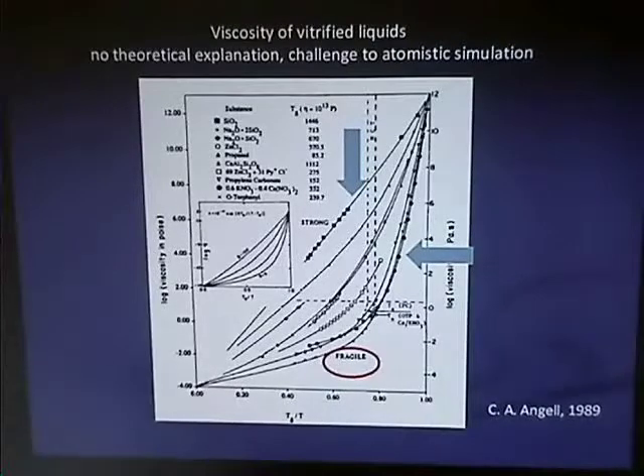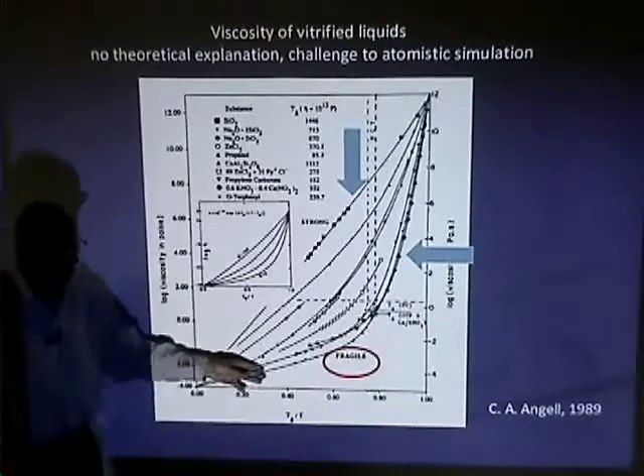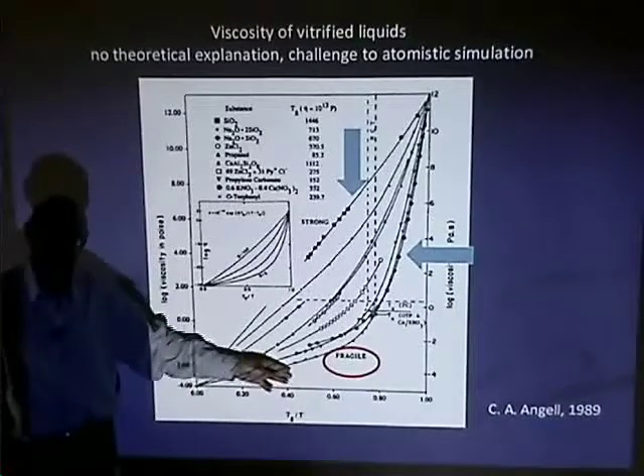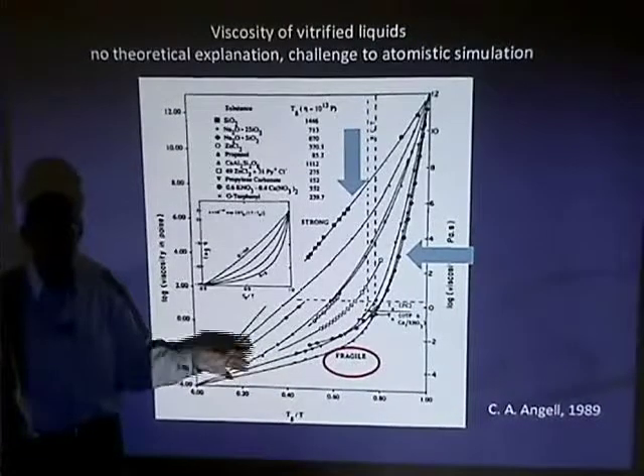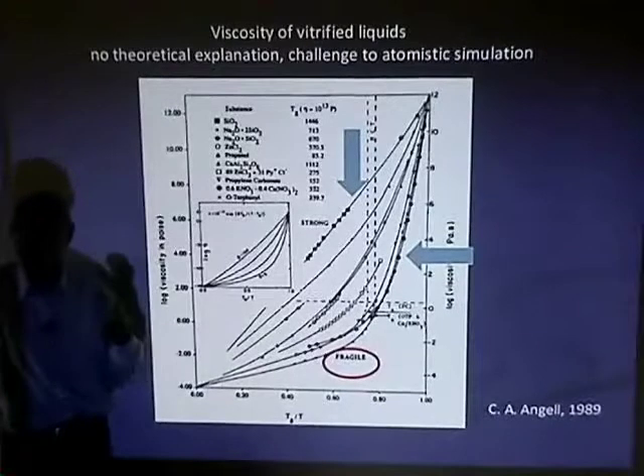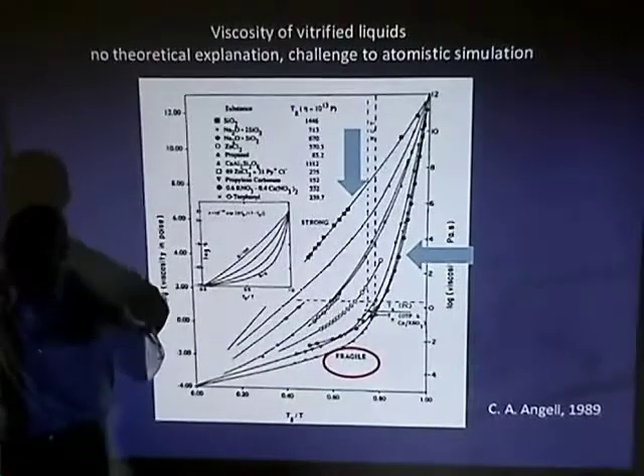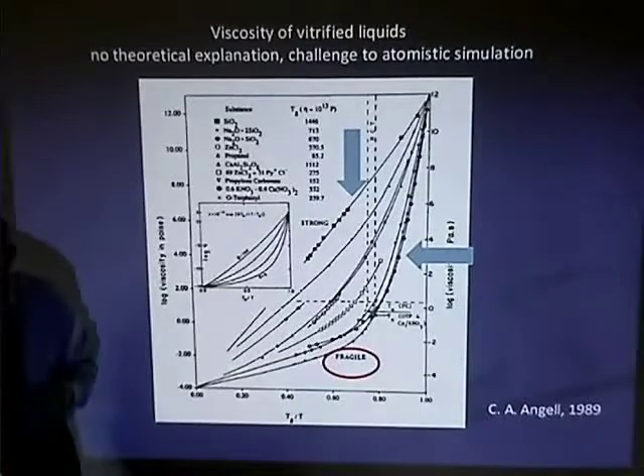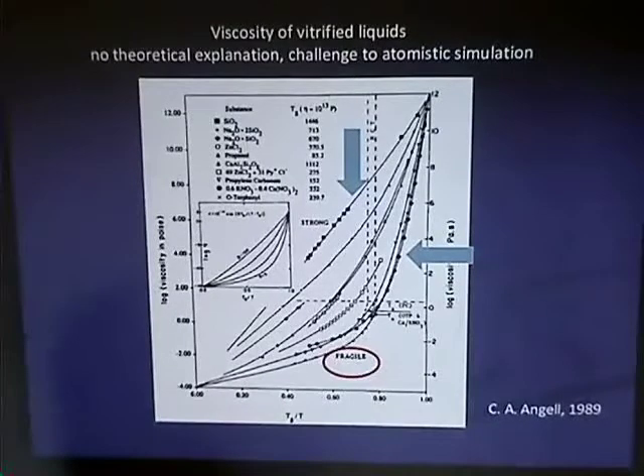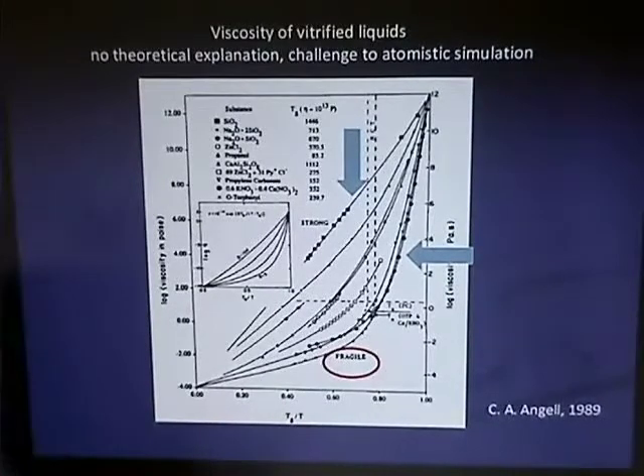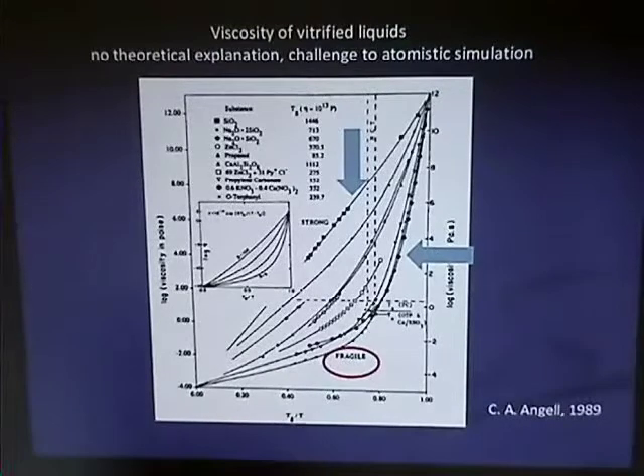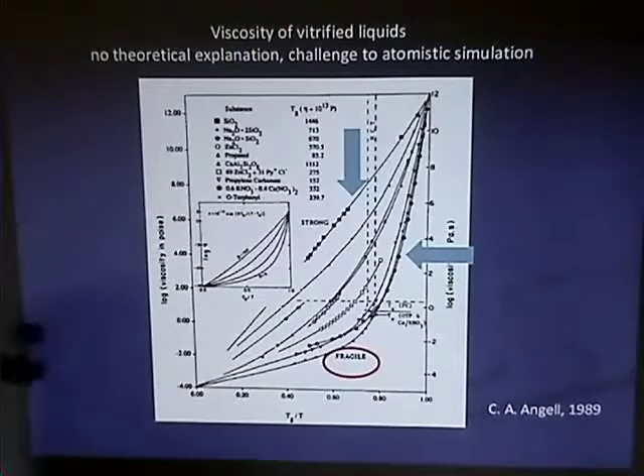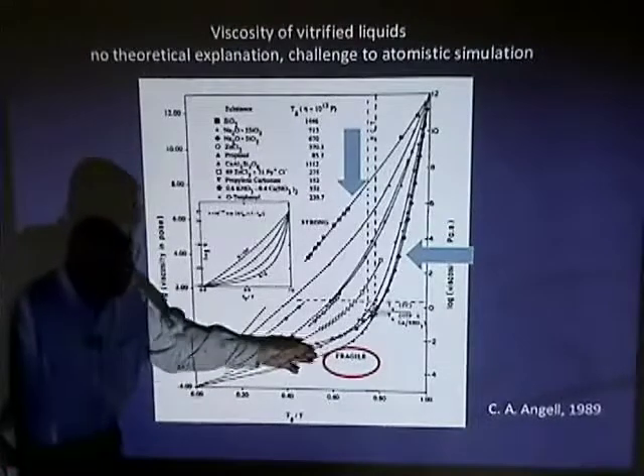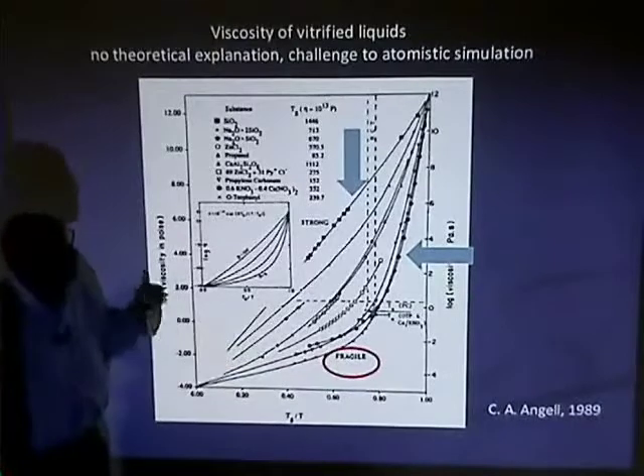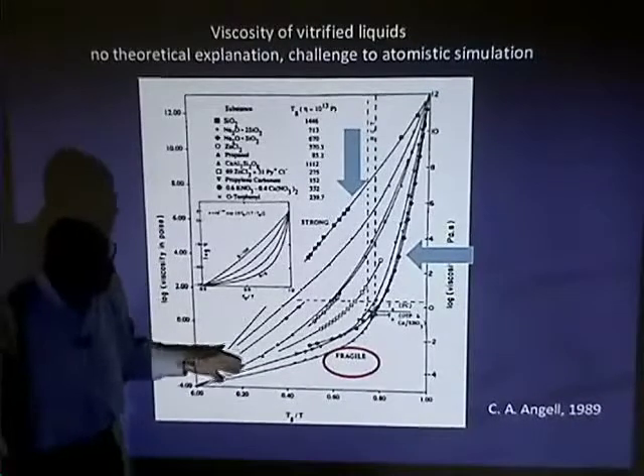Then you get into a regime where molecular dynamics runs out of gas, because the stress correlation doesn't decay anymore - you cannot simulate long enough. In other words, the relaxation time outruns your window of calculation. It's not to follow nature, it's just because we don't have big enough computers. Even if we have big enough computers, that's not the way to go, because eventually you're never going to catch up.